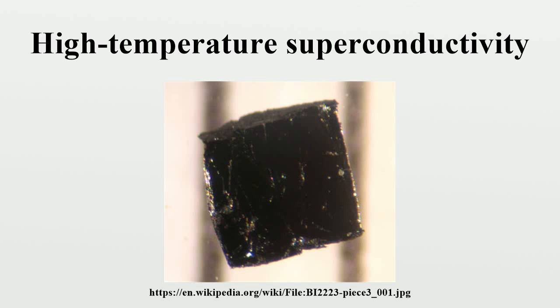It is noteworthy that the Tc of the Hg compound containing one CuO2 layer is much larger as compared to the one-CuO2-layer compound of thallium. In the Hg-based superconductor, Tc is also found to increase as the CuO2 layers increase. The observation that the Tc of Hg-1223 increases to 153 K under high pressure indicates that the Tc of this compound is very sensitive to the structure of the compound.